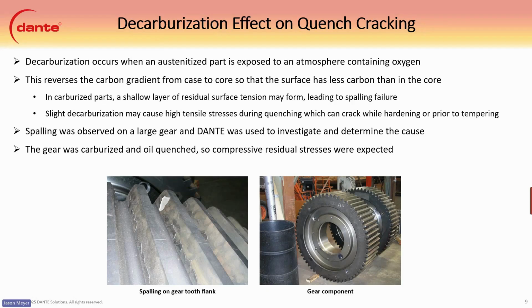So in general, decarburization occurs when an austenitized part is exposed to an atmosphere containing oxygen. And what happens is that oxygen helps pull the carbon out of the near surface, and results in a lower carbon value at the near surface of the part. And this reverses the carbon gradient from the case to the core, so the surface has less carbon. And then a shallow layer of residual tension stress may form, leading to the spalling failure that you see in this gear below. And the slight decarburization may cause high tensile stresses during quenching, which can also crack while hardening before tempering.